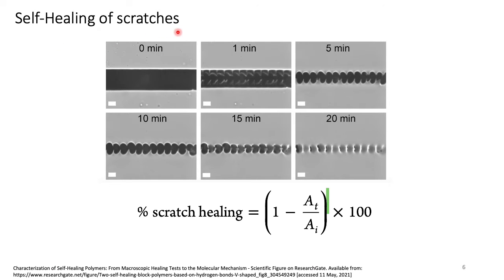In self-healing of scratches, the self-healing efficiency can be found easily by first scanning the area before the self-healing process starts, and then measuring the area after the self-healing process is done, and from that we can use this equation to find the scratch healing of the material.